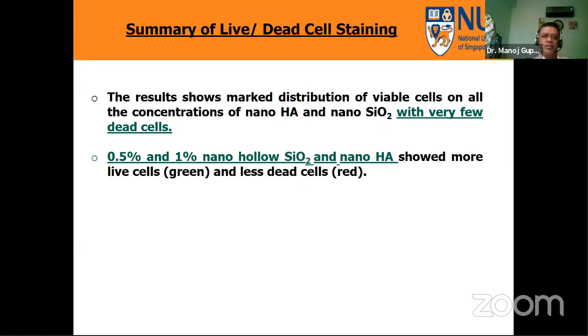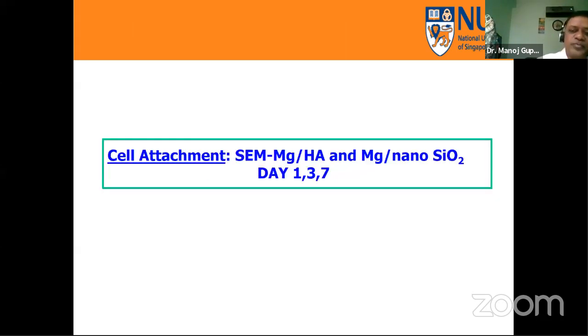What we learn from this live and dead cell staining is that for both nanohydroxyapatite and nano SiO2 compositions, we found very few dead cells. Based on all the results, observations, and quantitative analysis, we found that 0.5 and 1% nano SiO2 and nano HA, both in the same amount, show the best results in terms of cell proliferation and non-toxicity, with cells not dying.